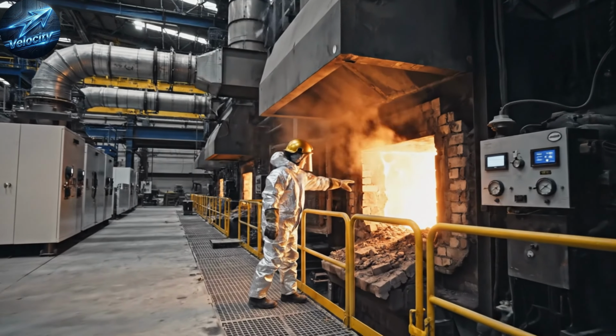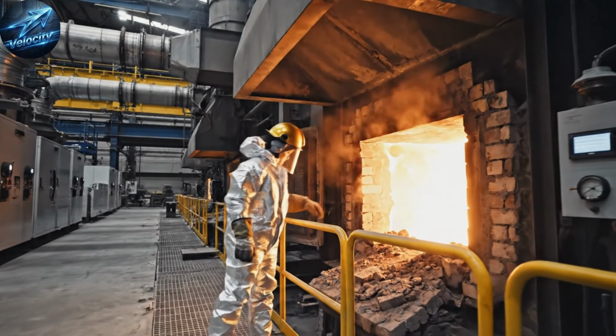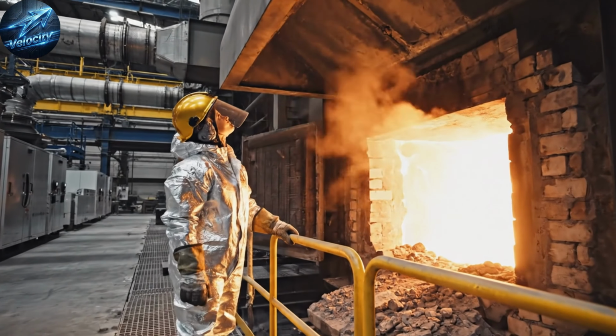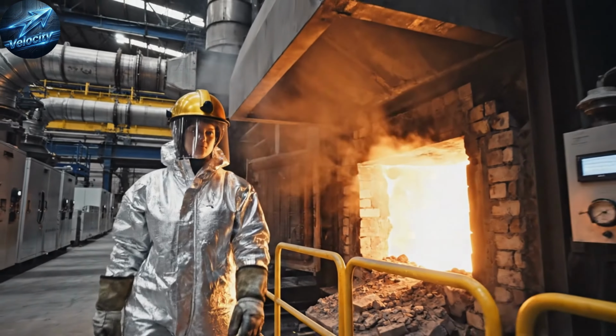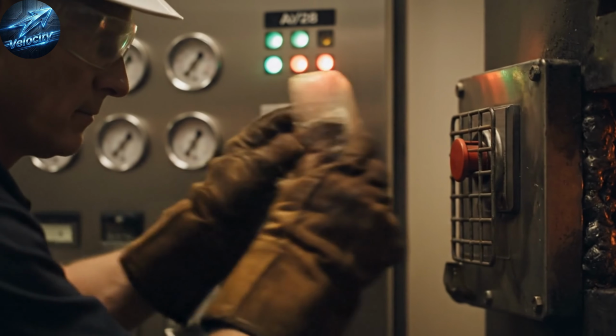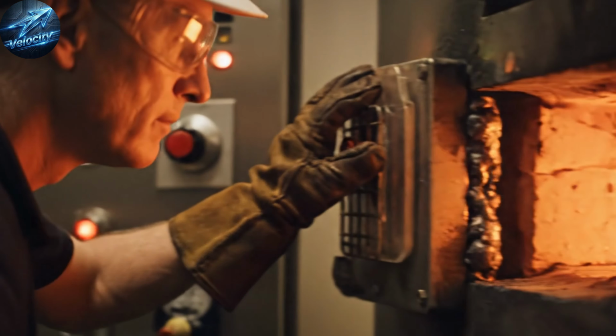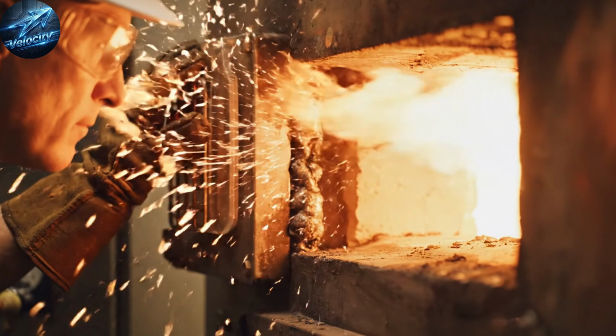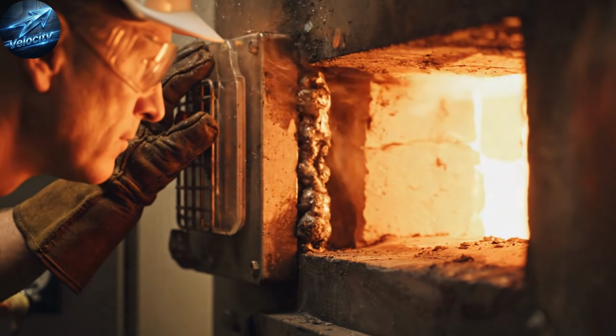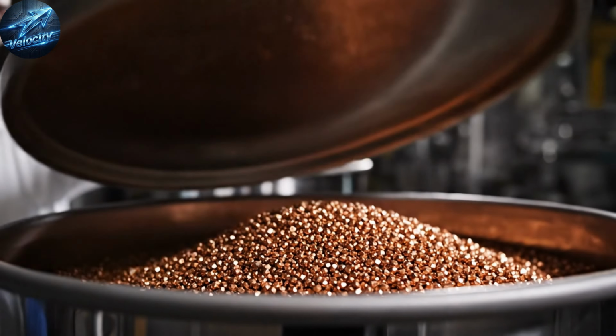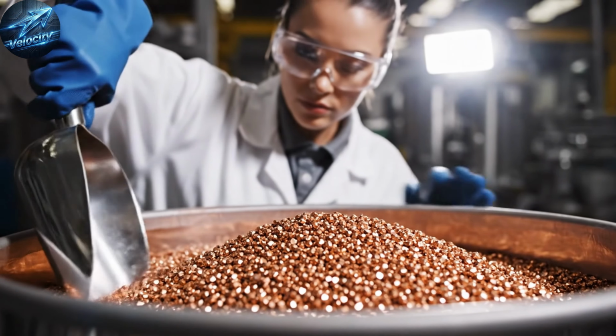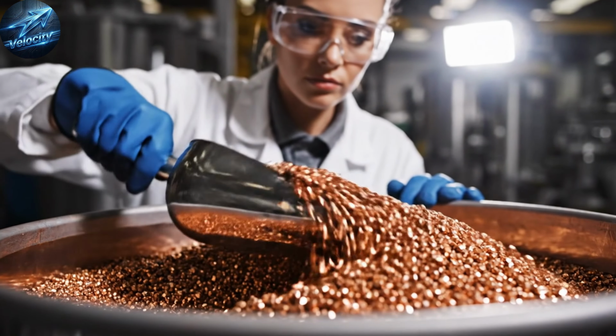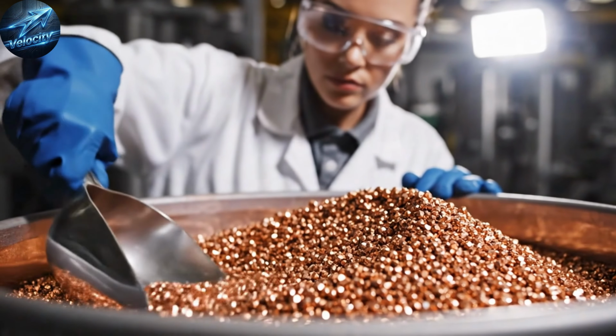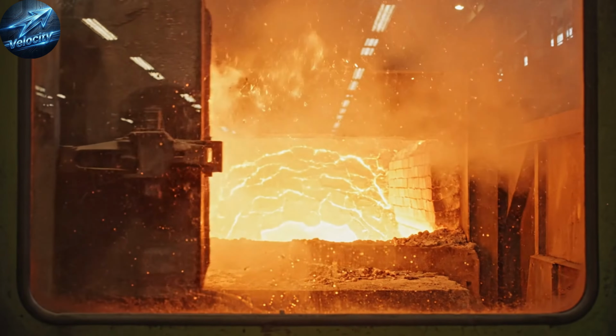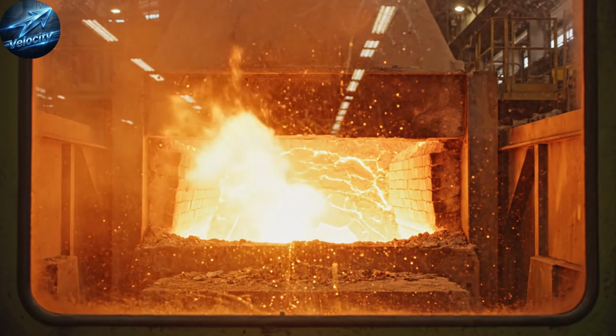A copper furnace doesn't forgive rushing. Charge too fast, too wet, or in the wrong order, and you get violent smoke, oxidation, and slag overflow. They build a stable hot bath first with clean, larger copper. Only then they feed granules slowly. Flux isn't extra. It's the tool that gathers impurities and floats them into slag. Watch the surface, color, foam, movement. One bad slag skimming moment can drag impurity right back down.